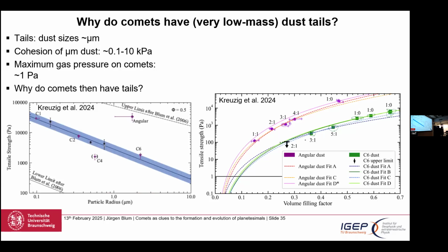So micrometer size has tensile strengths. If you imagine a clump or a pebble, the internal structure of a pebble of micrometer particles has an internal tensile strength on the order of a kilopascal. So we've measured lots of these samples in the lab. As a function of particle radius, here's a micrometer, here's a tenth of a micron, here's 10 microns. We measured the internal tensile strength at a porosity of 50%. And you're seeing we're in the range of 1 kilopascal, 10 kilopascals or so.